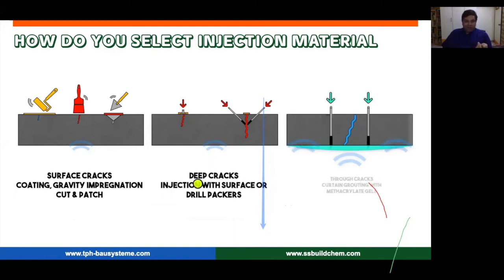As long as it's a basic kind of surface crack, not very deep, you can simply go with a waterproof coating on top of it. That should solve your problem. If your surface cracks are a little bit deeper, you can go with an epoxy impregnation kind of system. If it is still deeper, say more than about 3-5 mm, in that case you can cut out the crack or chase the crack, fill it with a polymer mortar, and then use a coating on top. That would be one of the best ways to do it.